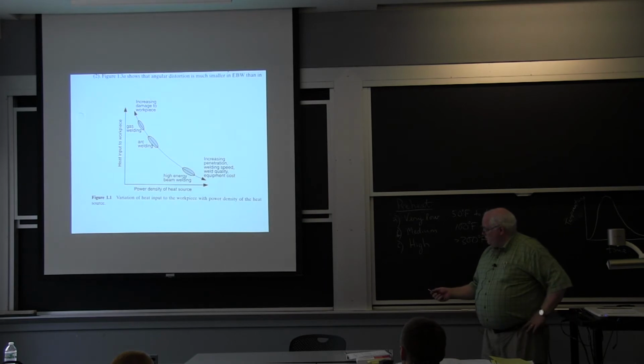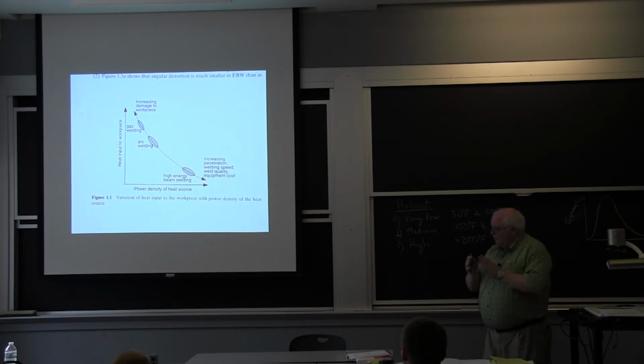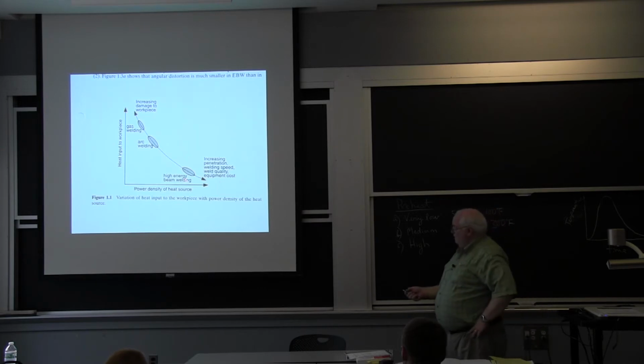where he basically shows heat input to the workpiece versus power density of the heat source for gas welding, arc welding, and high energy electron beam welding. And the real difference here is you get a very V-shaped weld here, less V-shaped in arc welding, and high energy electron beam you can get very parallel sides, and so there's no preferential distortion, greater shrinkage at the top of the V than the bottom of the V.